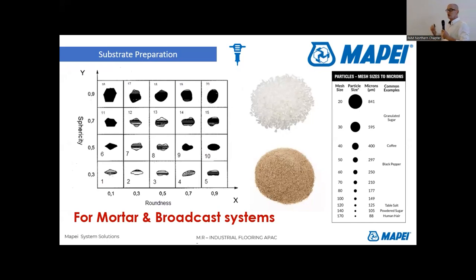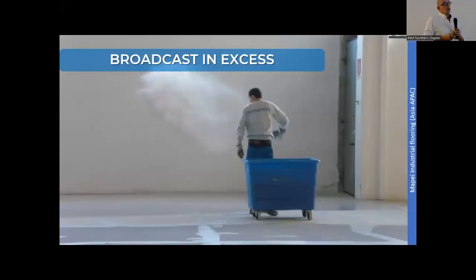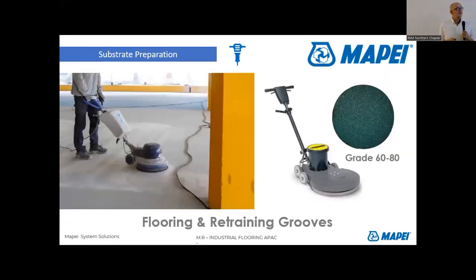So it also means quality. Ours makes 50 newton per square millimeter compressive strength. A total difference compared to the site mix. It needs to be specified. Not that we say make a site mix of 5 millimeter epoxy, but no, specify really. So we're doing sand and quartz sand application sometimes to lift it up.